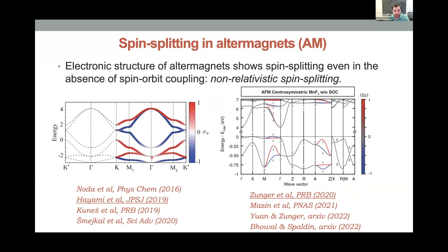But the main idea here is that the splitting, as we're going to show, can be much larger than any electronic scale, and it doesn't require spin-orbit coupling. So that's why it's different than, for example, non-collinear magnets or non-centrosymmetric systems that have a spin splitting that depends on the spin-orbit coupling.